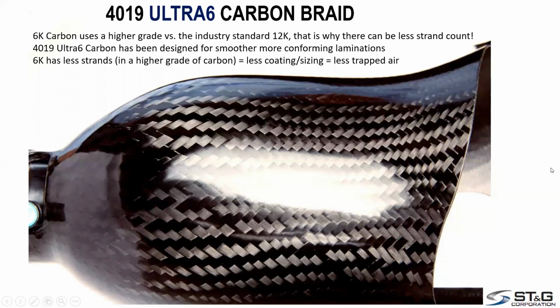Ultra 6 carbon is a higher grade carbon than is used in the industry standard of the 12K carbon that you normally would get. So yes, you do have less strand count. You have 6,000 strands versus 12,000 strands, but you get a higher grade carbon. So the strength is about the same. Now the one thing you will get out of the 6K versus the 12K is it will lay on your cast smoother. Also when you laminate it, it will lay flatter. The nice thing too is because there are less strands, there's less coating to deal with. Also, with that, you'll have less trapped air.